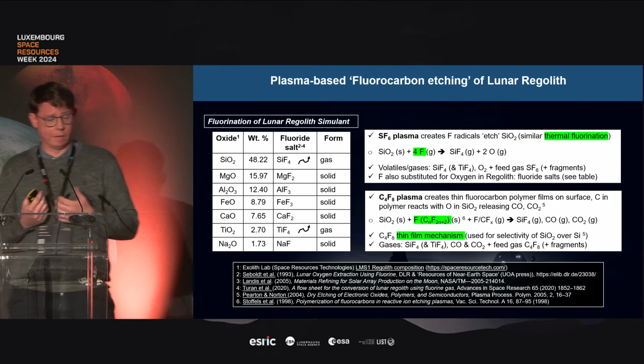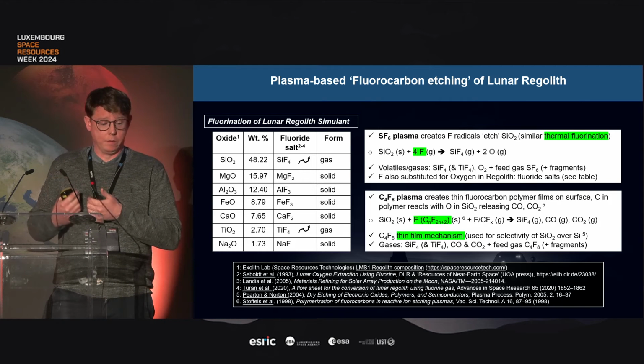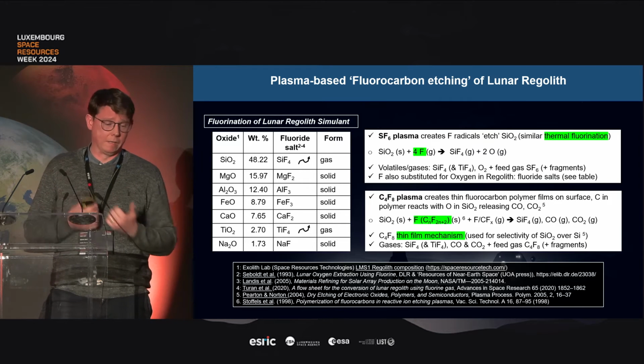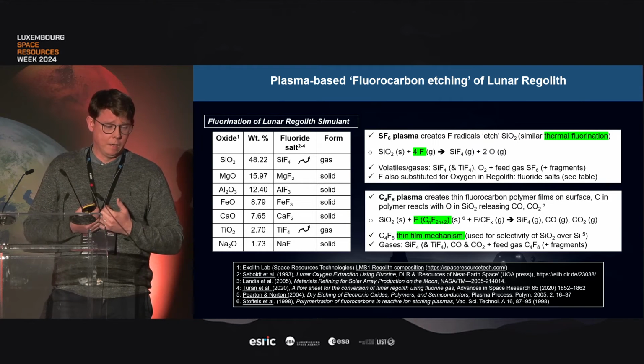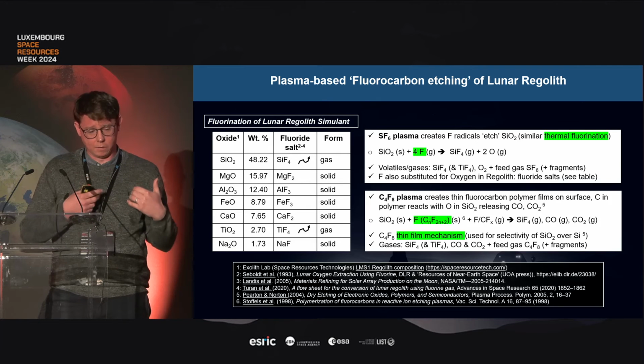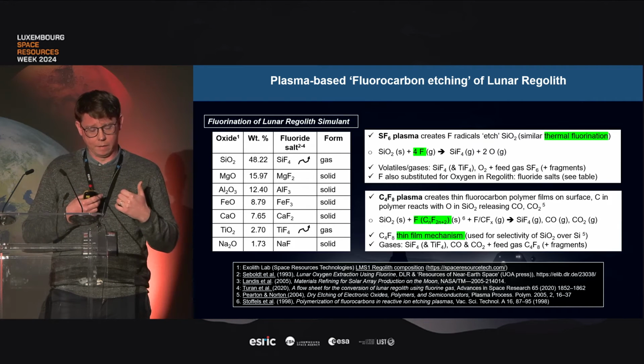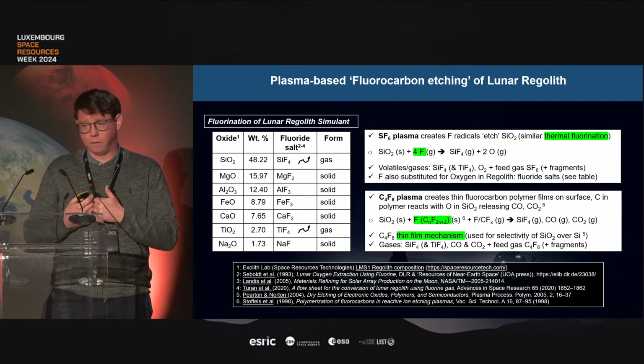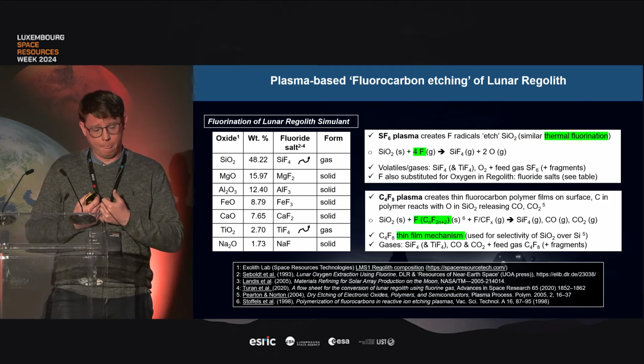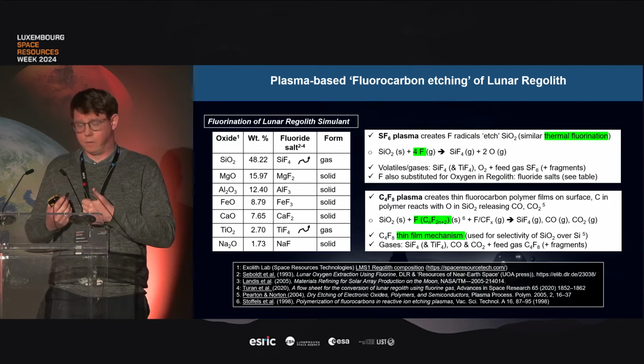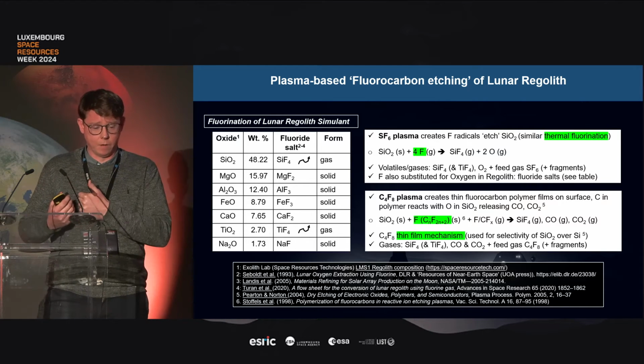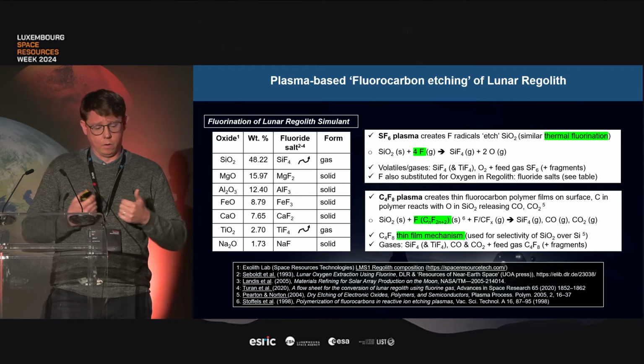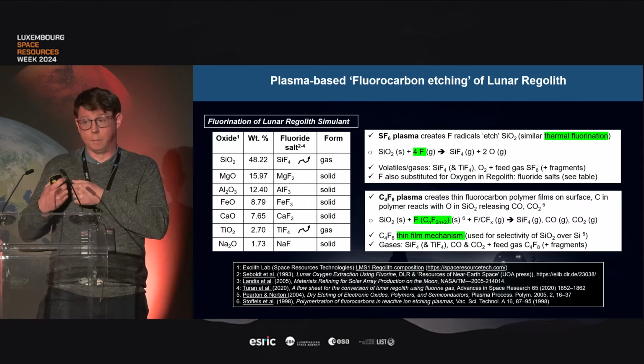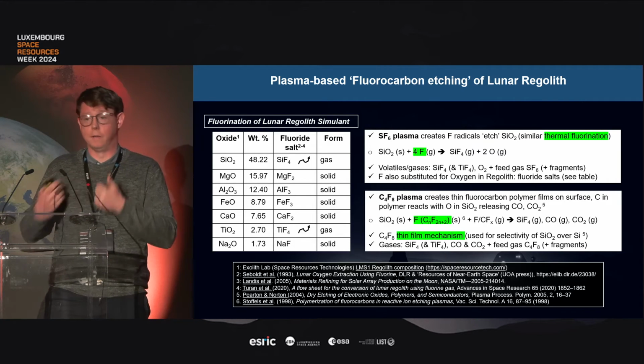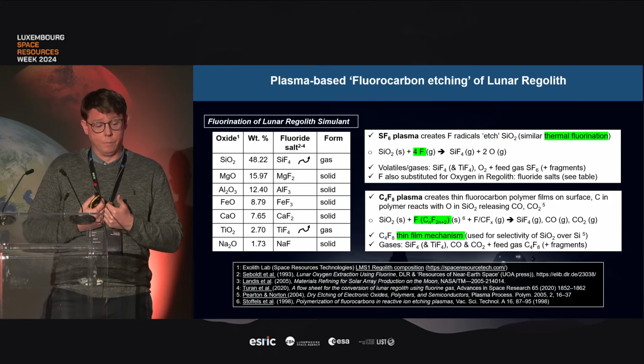So this is the penultimate slide of content, just to give some insight into what we think is going on in terms of the chemistry. On the left-hand side is the oxide component of the regolith that we're using. The expected fluoride salts, of course, silicon tetrafluoride, SiF4, is volatile, and also this fluorine is going to be deposited to substitute the oxygen in the regolith itself.